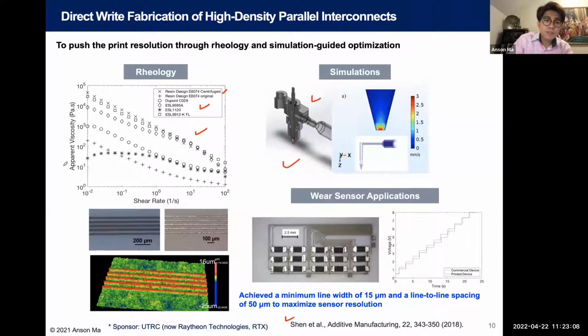So it comes back to this rheology curve again. This is apparent viscosity versus shear rate. All these materials shear thin. Again, the viscosity decreases as a function of increasing shear rate. And in this kind of printing, usually this is perceived to be a good thing, because when you're pushing on the ink material, the viscosity drops, right? So it doesn't take a lot of energy or pressure to drive out your material. So that's a good thing.